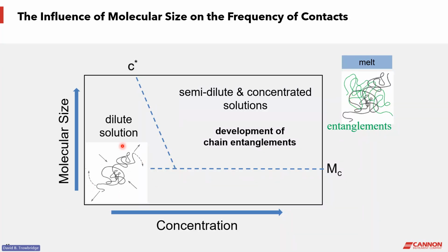This is the state that's necessary and required to get intrinsic viscosity from the DSV measurements. The solution viscosity theories require this, and it's not even remotely the case for the melt flow state. So you have to be cautious if you hear or see numbers provided for intrinsic viscosity based on melt flow, because the state does not correspond to the free rotation and extension and compression that's required for the theories.